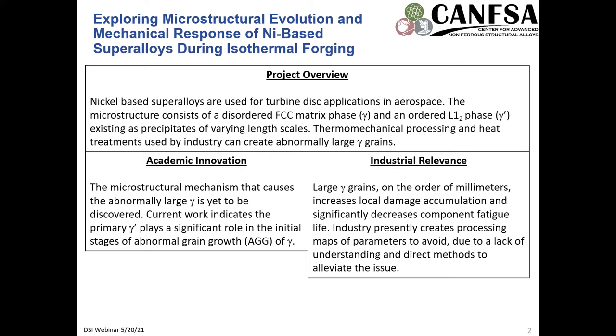And the thermal mechanical processing and heat treatments that are utilized by industry have been shown to occasionally create abnormal grain growth or abnormally large gamma grains. And from an academic perspective, the innovation for this project comes in that this microstructural mechanism is not yet fully understood, or even really understood at all, as to what is causing this abnormal grain growth. And current work and some review of previous literature has indicated that the primary gamma prime that is incoherent plays a significant role in the initial stages of abnormal grain growth of the gamma.